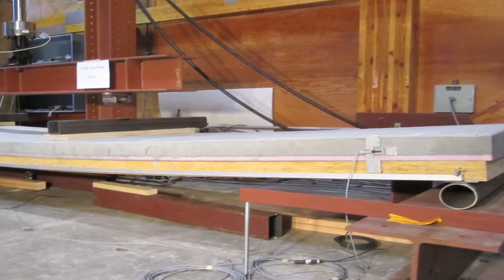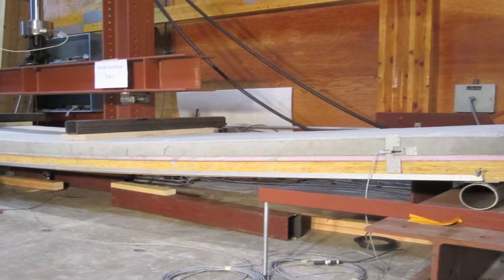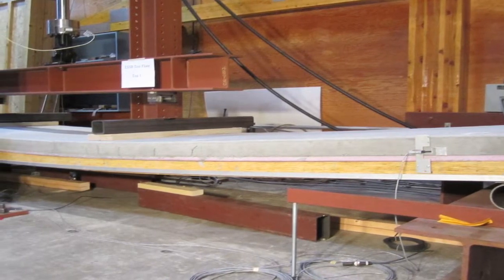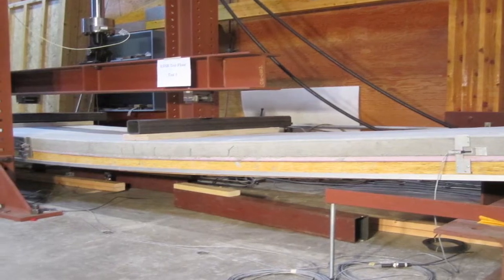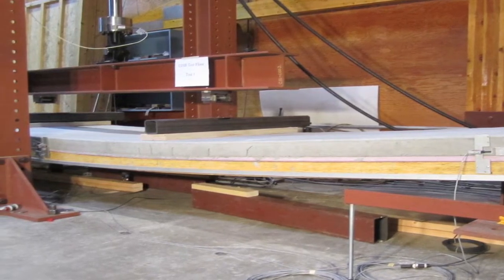The bending test is the next step — you actually go from a little specimen into a building component. There's also thermal testing; you have to test it under fire conditions. All those tests on the composite system had the final result that the weakest element in the composite cross-section is the steel. We had that on the static test and we had that at the fatigue testing conditions.